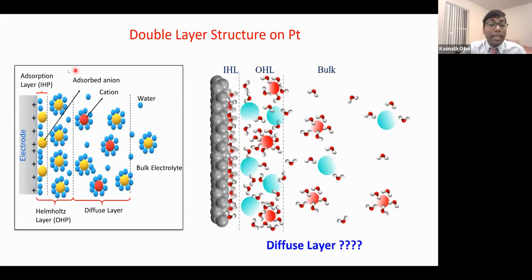Now that leads, basically, earlier, if I explained rightly, to the double layer structure: you have an ion and a counter ion, depending on the charge, the counter ion in the outer Helmholtz layer, and then the distribution of all the ions in the diffuse layer. And in the case of platinum, all those ions come close to the surface. That means you do not really have a diffuse layer at all. So the ions are moving much closer and there is very little diffuse layer, or almost none. That's a typical double layer structure on platinum. And probably that's why platinum is so active and used as a catalyst in many cases.